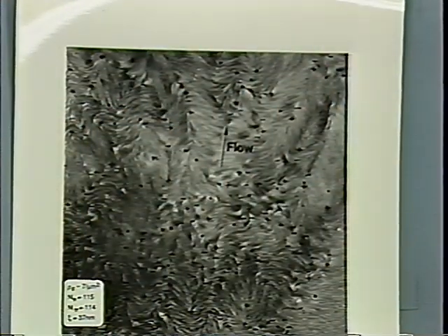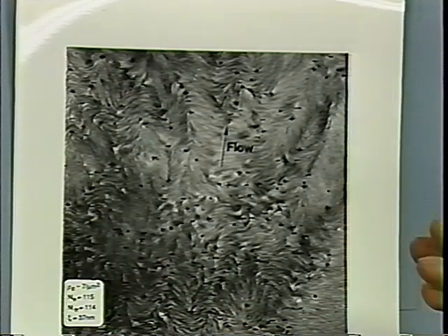Those disclination lines would come around, and maybe a plus line would come back as a minus line and form a loop. This would be a disclination line in space in the bulk of your material. As the two approach, the loop shrinks to smaller and smaller regions, and then it would disappear. Or if you generate defects, you would go the other way around.